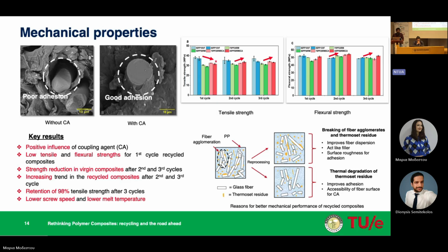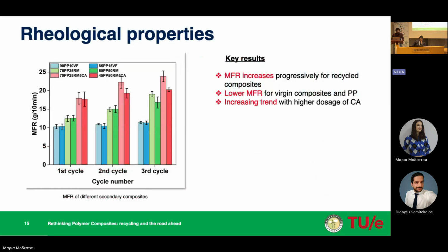And also, since we are using the temperature zone somewhere around 180 to 200 degrees Celsius, there is a slight possibility of thermoset residue getting degraded, which will obviously create a smooth surface, which will help the coupling agent to enhance the adhesion between the fiber and matrix. So yeah, in this case, I would say reprocessing actually helps the composites to enhance their mechanical properties and to give better performance. And moving ahead, we also need to think about the rheological properties which need to be addressed because